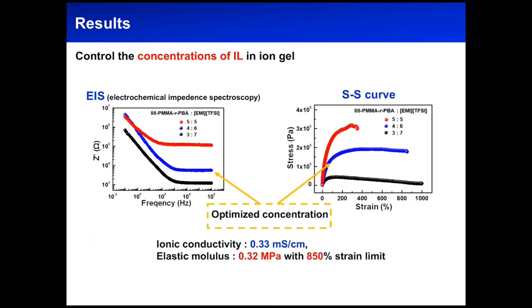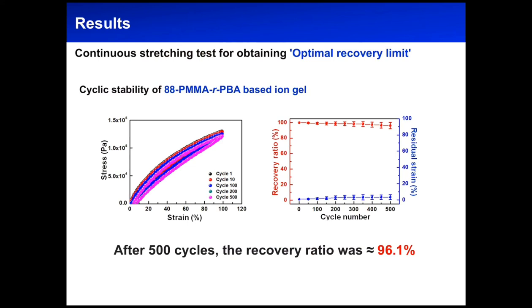Moreover, the concentrations of ionic liquid are main factors for evaluating the ion gel's property, such as mechanical strength and ionic conductivity. In literature, the two main characters are in trade-off relationships. So, we precisely controlled the concentrations and measured the ionic conductivity and mechanical strength. Therefore, the optimized concentration was fixed, which shows high stretchability and moderate ionic conductivity. We further examined the cyclic stretching and releasing stability at strain 100%, in which similar stress-strain curves were still recorded after 500 cycles. Mechanical reversibility was quantitatively characterized in terms of recovery ratio and residual strain. After 500 consecutive cycles, the recovery ratio was 96.1%, and the low residual strain level was maintained.